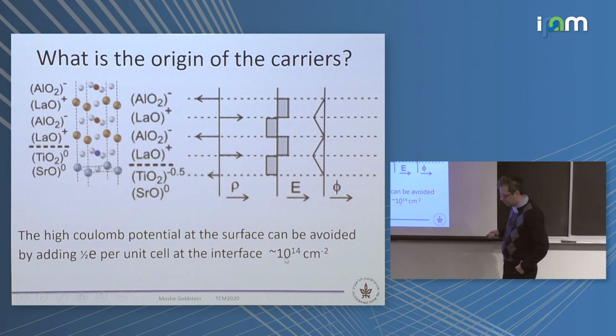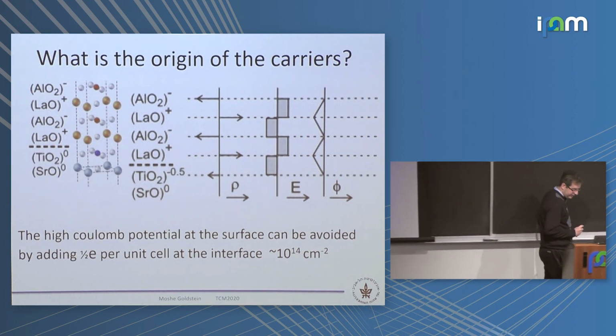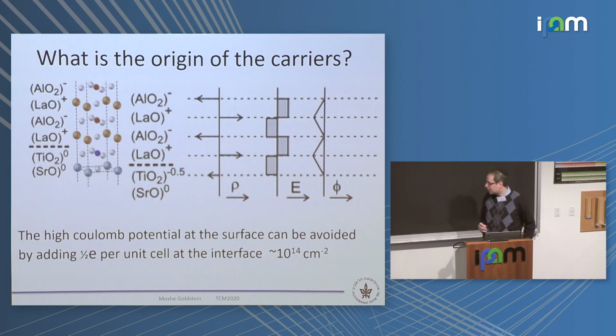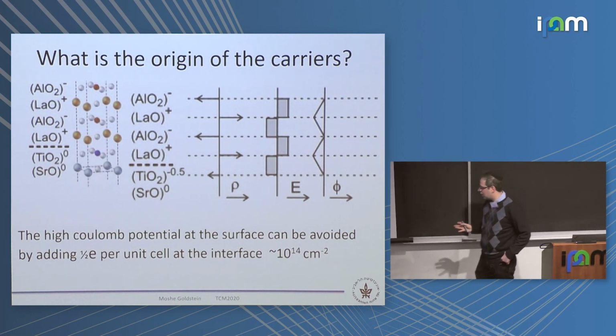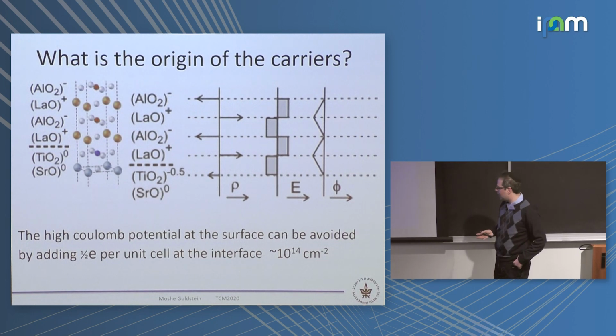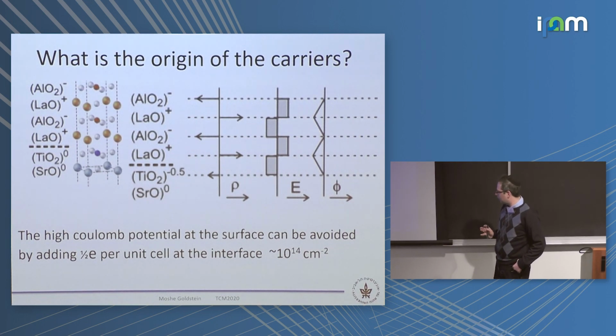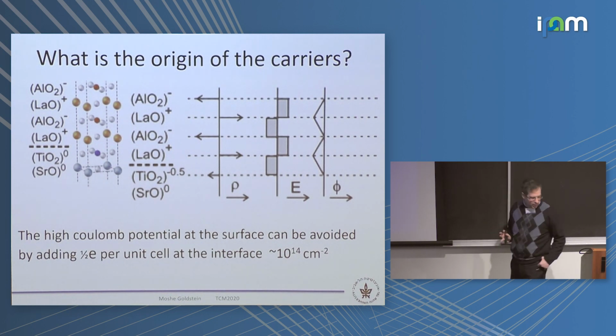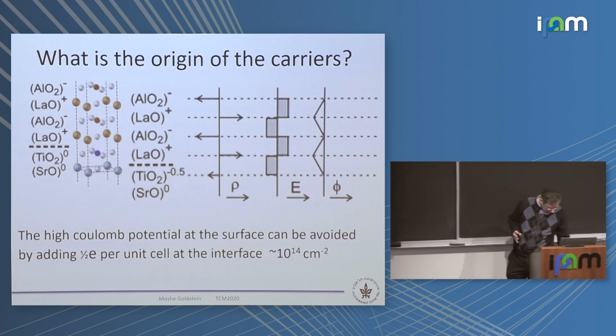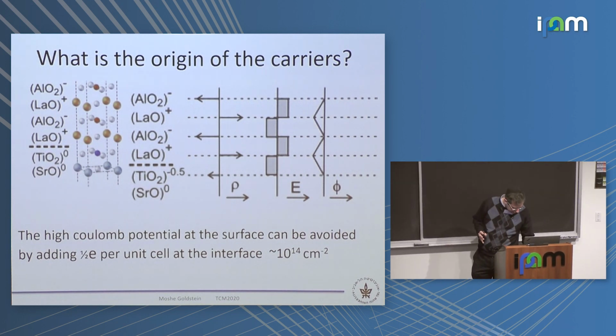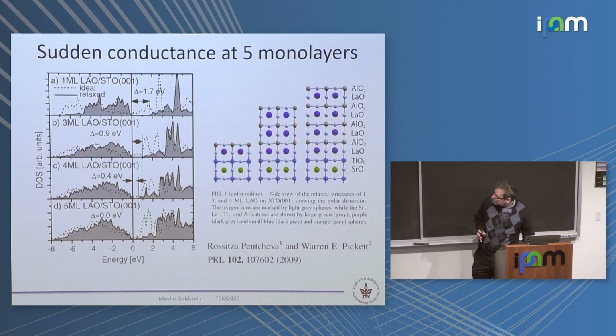So ideally, the system should transfer 1/2 of an electron per unit cell, which corresponds to a density of 10 to the 14. Now, when you measure transport, you see that the system indeed becomes conducting, but the number of carriers that you see that are mobile is way less than that. This is a bit of an open question to which there is no good answer, but it's accepted that most of the carriers are trapped somehow, and only few of them actually go to the right bands to take part in the conductivity. We'll see that.